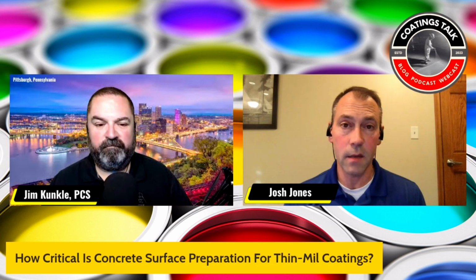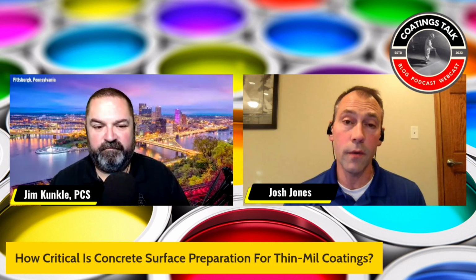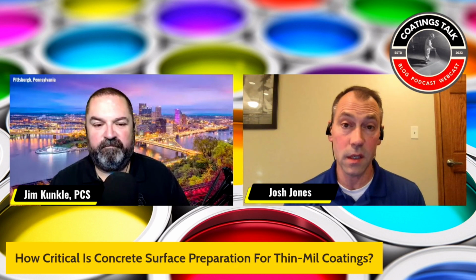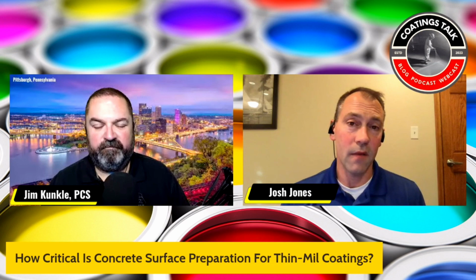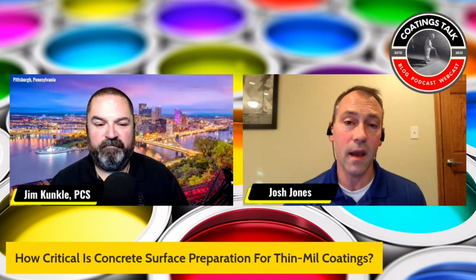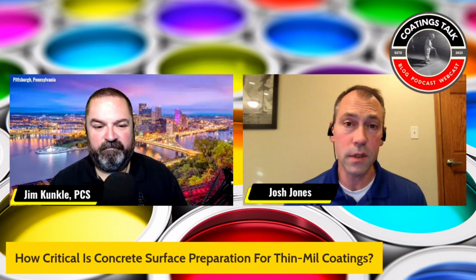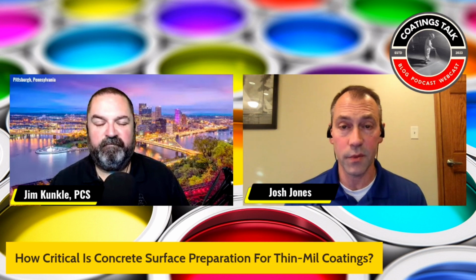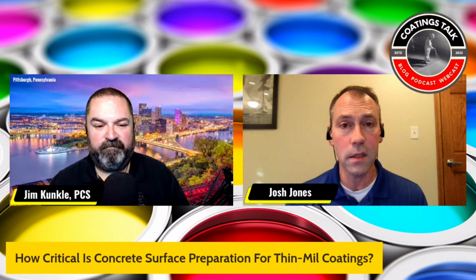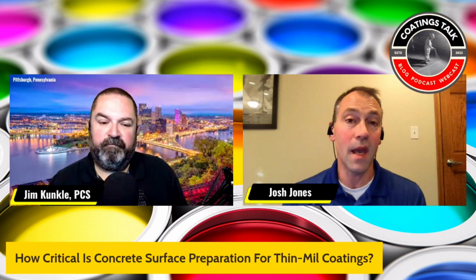Concrete is a mixture of sand, Portland cement, and aggregate. As long as I can make that surface open, and I know that happens when I grind it because it goes from whatever color it is to basically a white, that's all those fractured sand crystals that are now, once clean, thirsty. It also is helpful to consider grinding because it's very rare that I'm going to only have floors that are just clean concrete that need to be ground and coated. There's usually going to be something on there like a cure and seal from the placement of the concrete. Existing spaces may have adhesive, may have paint, may have coatings.